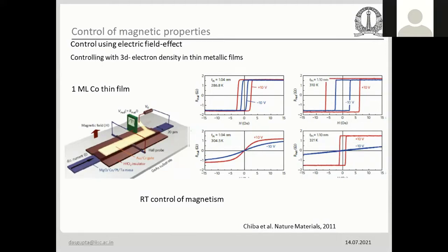On the other hand, for a pure metal like copper, it can be only 0.5 angstrom. So you can see that it's a large difference. And why this large difference? Because of the carrier concentration of the said material. A metal has a very high carrier concentration, a pure metal, and therefore it can screen any external field very effectively. It doesn't allow it to penetrate much deeper. It can screen within sub-monolayer of atom.